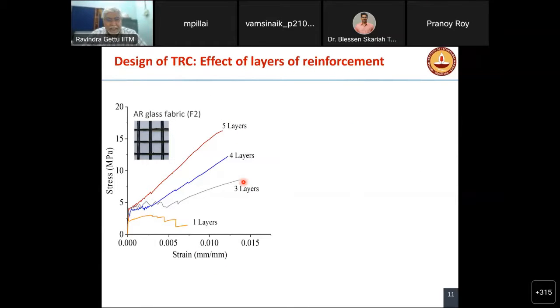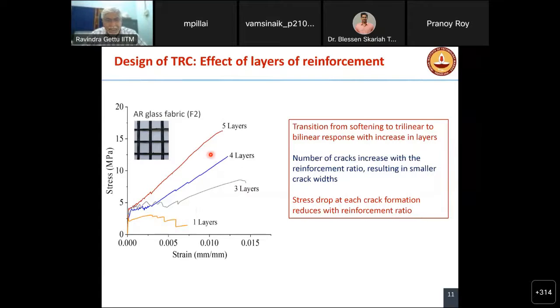The same effect we see when we increase the number of fabric layers. Instead of going with few layers, if you increase the number of layers, you see that it becomes more and more bilinear. There is a transition from softening to trilinear to bilinear. So this is what we believe is an ideal material behavior. So we design the material such that you will have a response like this. So we put the number of layers in order to get this. So we get a behavior like this. So this is what we are aiming for.